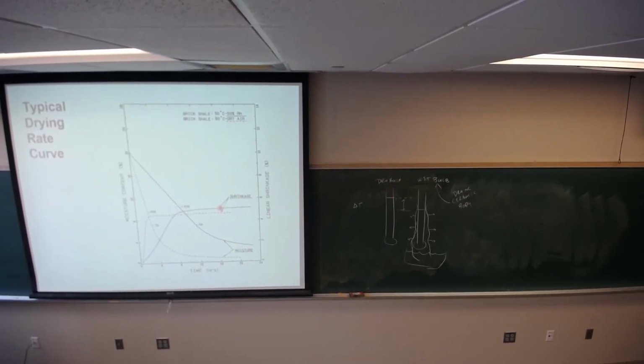Now, when I say it's not a drying problem, but it shows up there, you can say, well, doesn't that make it a drying problem? Well, my point is this. I get cracking in the body on drying. If I dry it slower, the argument is, oh, I'll avoid the cracking. But my argument would be that's not true. It's not the evaporation rate of water from the surface. It's the ability of particles to rearrange and compensate for density gradients. If you're unable to do that, it doesn't make a difference how fast or slow you dry it, you get cracking because you have large density gradients.